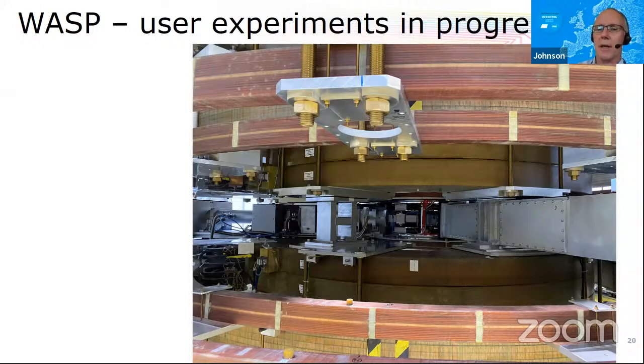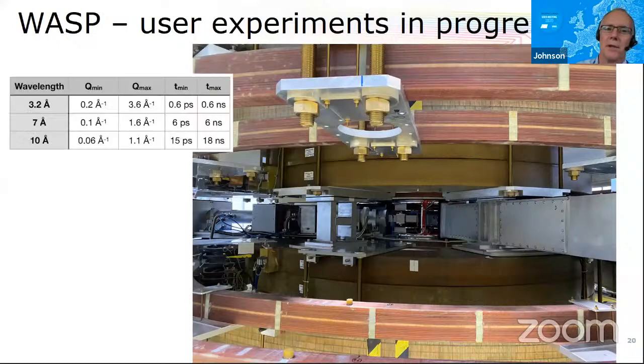So what you see in this photograph is that the coils have been turned vertically, essentially, and if you think about it, the magnetic field lines that are in the scattering plane in the middle of this photograph are the same as you would get from the horizontal coils, and they allow the neutron spins to precess around those field lines as they go from the sample here out to the detectors on the edge of the instrument. So this way we get a very wide scattering angle, which really increases the count rate on this type of instrument compared to its predecessor, IN11.